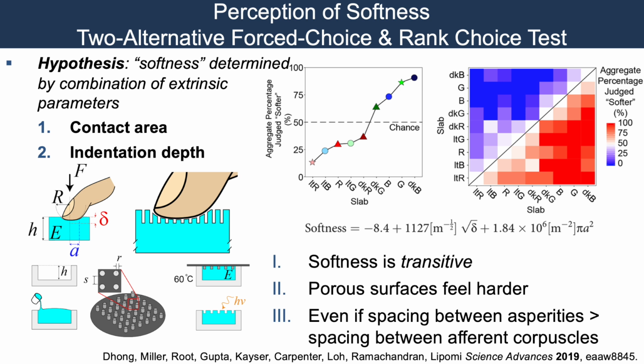And softness, we had an idea that you would be able to differentiate surfaces based on softness based on the contact area that your fingertip makes with the surface, as well as indentation depth. And the problem is, if you buy a slab of material from Home Depot or the hardware store that's isotropic and unstructured, it turns out that your indentation depth and contact area are going to increase monotonically with each other. It's possible to divorce these parameters somewhat from each other by microstructuring the surface, and also that controls the contact area.